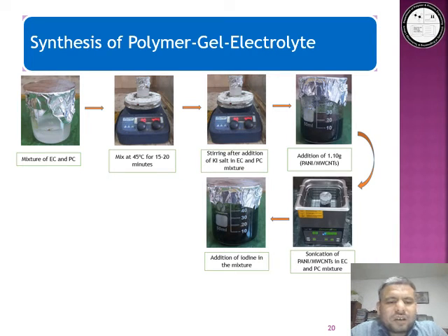After that, a fixed amount of nanocomposite was added at 100 centigrade with constant stirring for 2 hours to achieve a homogeneous solution. Finally, iodine was added to the above solution and the whole mixture was kept at a constant speed for 15 to 20 minutes. The other electrolytes with different salt concentrations were prepared in a similar way.